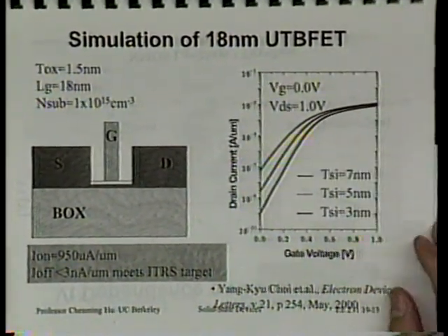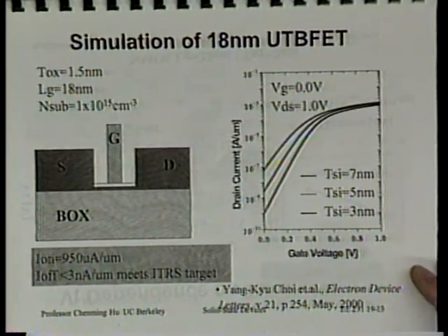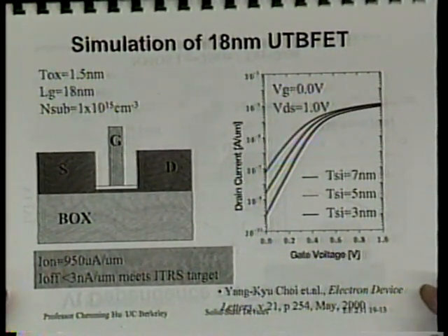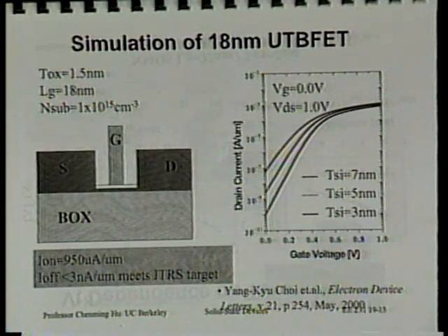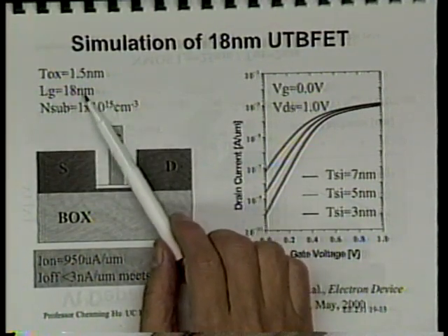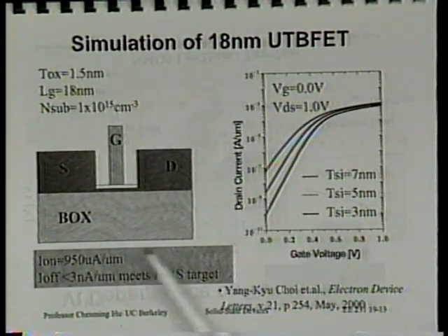And so, because of the processing capability limitation we have, we cannot really push this device to the smaller scale we want. So we also use some simulation to extend our experimental data. Once you have some experimental data, you can calibrate the simulator and have some confidence in it, right? If you don't have any experimental data, people don't want to believe your simulation. But once you have experimental data, people are willing to see what the simulator says, how much more you can do. So when we simulate similar conditions, 1.5 nanometer, 18 nanometer gate,